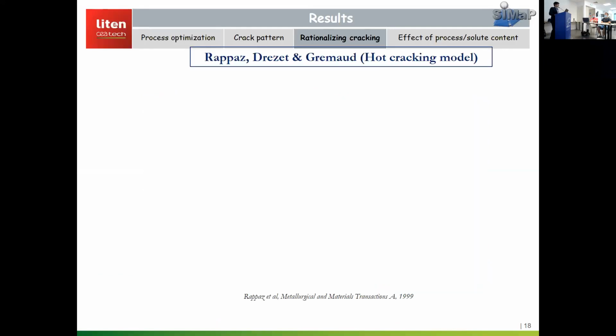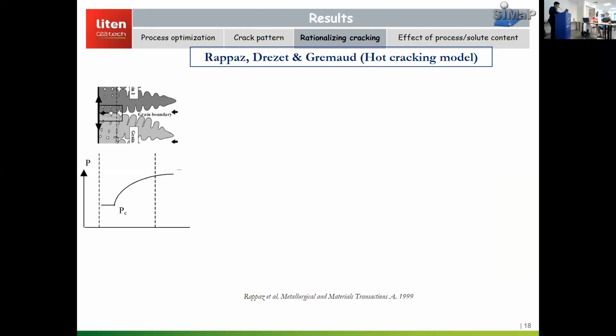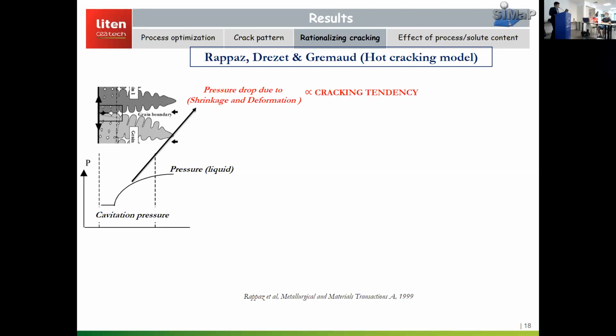So now moving further, we thought, okay, let's use a very predominant model, the Rappaz-Drezet-Gremaud hot cracking model, to understand the initiation of cracking. When two dendrites are growing along the thermal gradients, in the RDG model, they try to understand the pressure drop in the mushy zone as a function of distance. For example, the pressure in the liquid starts to decrease and reaches a particular cavitation pressure, and once it reaches this cavitation pressure, you nucleate a cavity, and this leads to cracking. This pressure drop is due to shrinkage and deformation. So the higher the pressure drop, the higher the cracking tendency.